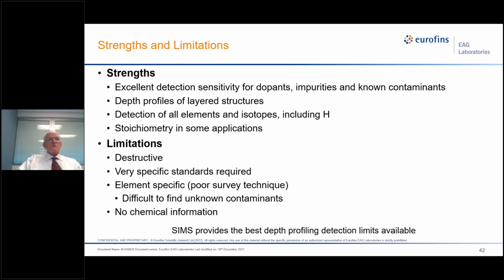However, you may be stuck with SIMS, because SIMS, among the surface analytical techniques, is the only technique, as shown from the smart chart, that will have a sensitivity of less than 0.1 atom percent, which is kind of where XPS and Auger run out of steam. So that's the reason you use SIMS. Despite all the problems and limitations, it's sensitivity. That's why you use it. And I want to point out here at the bottom, because we're sputtering and tearing up the sample, there's no chemical information available with depth profiling SIMS. And many of you ask about that. Sorry, can't give it to you.